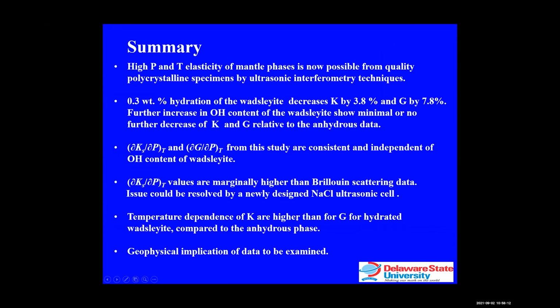One minute. Yeah, so in summary, we've seen that we can now have high temperature, high pressure elasticity data of mantle minerals by making measurements with the ultrasonic interferometry technique. We also showed that 0.3 weight% of hydration of the wadsleyite decreases K and G by 3.8% and 7.8%. And further increase in the water content does not seem to have any significant effect on K and G. We show that the pressure derivative of the bulk modulus so far is independent of water content, and that we can resolve the issue of the K pressure derivative by modifying the cell, introducing sodium chloride. So that's it for this part.